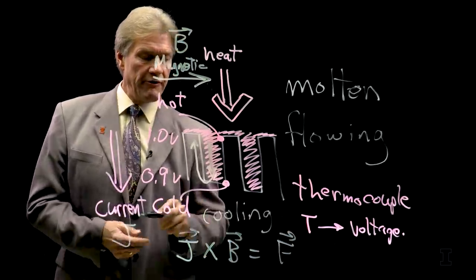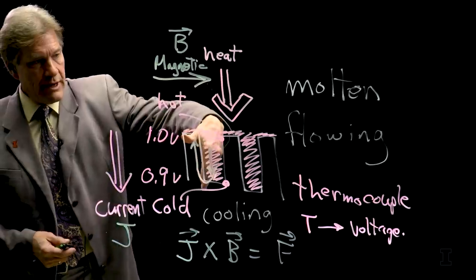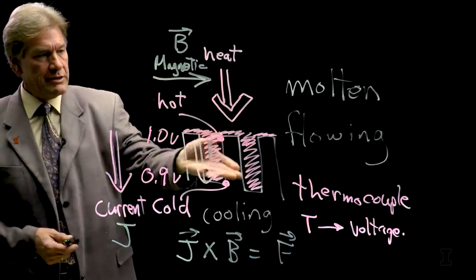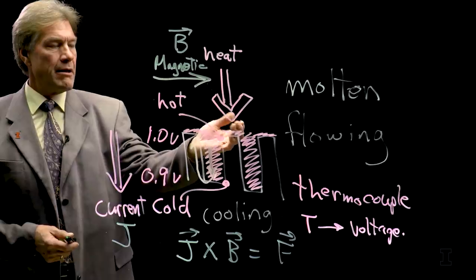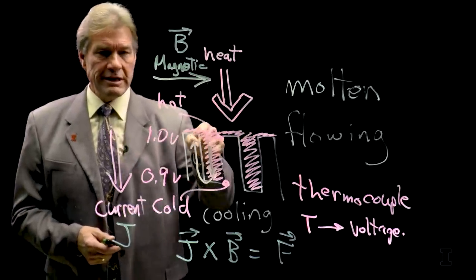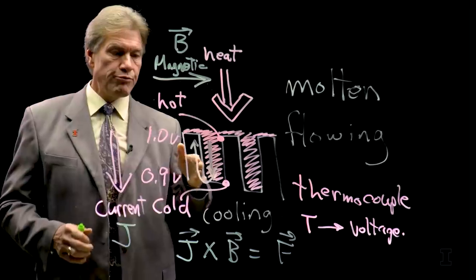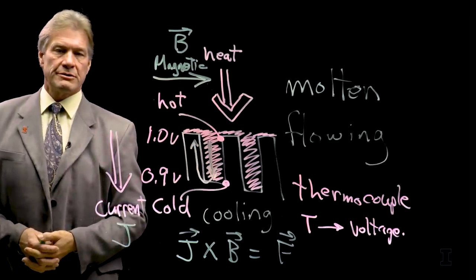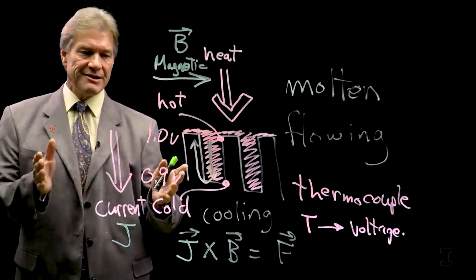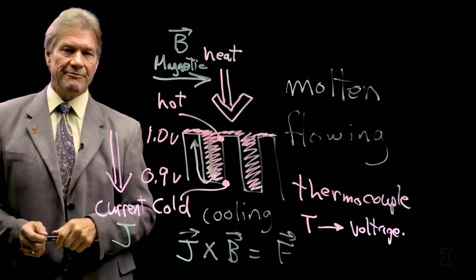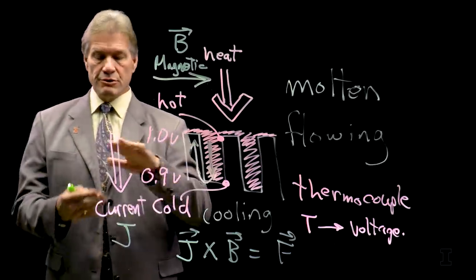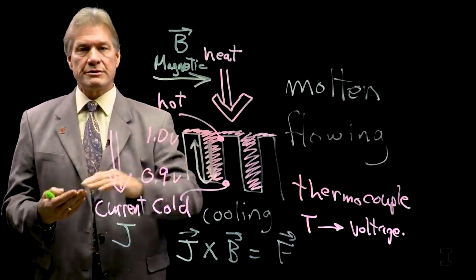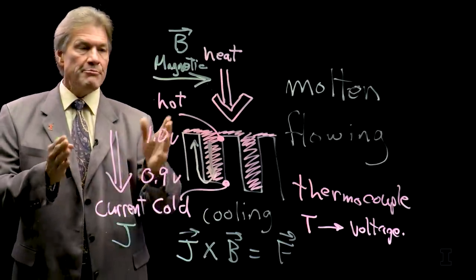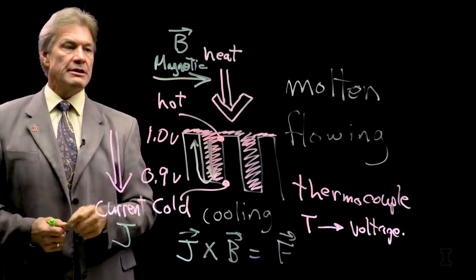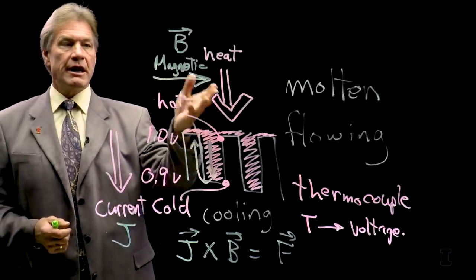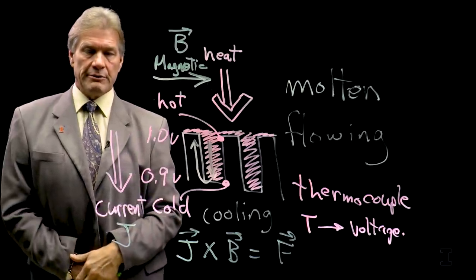There's a force called J cross B equals F, force. And if I have my current going this way, my magnetic field going this way, I will get a force in and out of this board, and it will push the lithium across the trench. The hotter it gets, the faster the lithium will flow. And this allows us to move this clean lithium across the surface, self-propelled by the two things the plasma gives us. The plasma gives us the heat, and the plasma has the magnetic field.